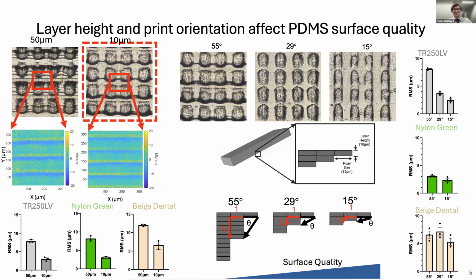This is indeed what we see when we look at the effects on the surface smoothness, or the RMS. However, the surface quality isn't the entire story. While the 15 degree is a little bit smoother, we do see a little bit of distortion of the microwells compared to the 29 degree. Ultimately, we selected the 29 degrees to print rather than the 15 degrees.